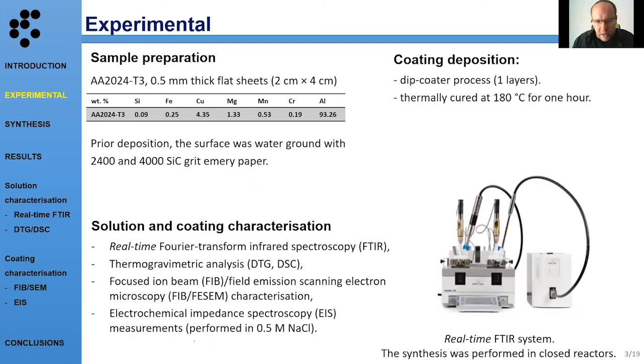So here is the experimental part. As I mentioned at the beginning, we have aluminium alloy 2024. Here is the composition. Prior to deposition of the coating, the surface was wet ground with silicon carbide emery paper to obtain a smooth surface, and this was prepared for coating deposition. All coatings were synthesized in this closed reactor because we tried to prepare the best conditions to get results which can be repeatable after a certain time. The reason is also that we want to follow the reactions every minute with an FTIR system.